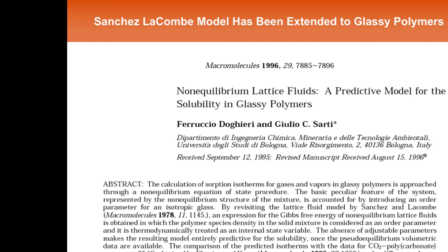Okay, and what that means is that it has a very open structure, lots of free volume, and glass transition temperature is in excess of 250 degrees C. This material will thermally decompose before it will go through a glass transition. It really doesn't like to be in the rubbery state. And so then you can expect that it will exaggerate the non-equilibrium sorption and ultimately transport and other properties.